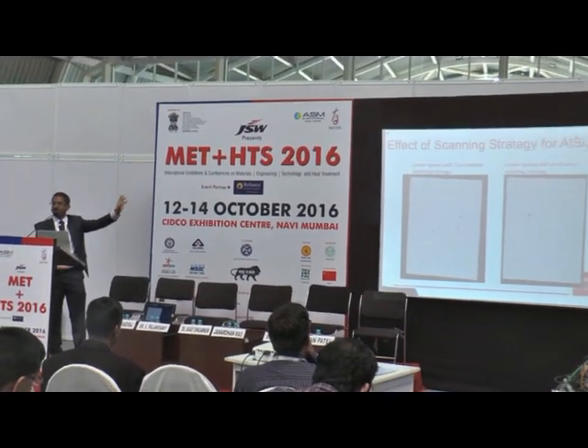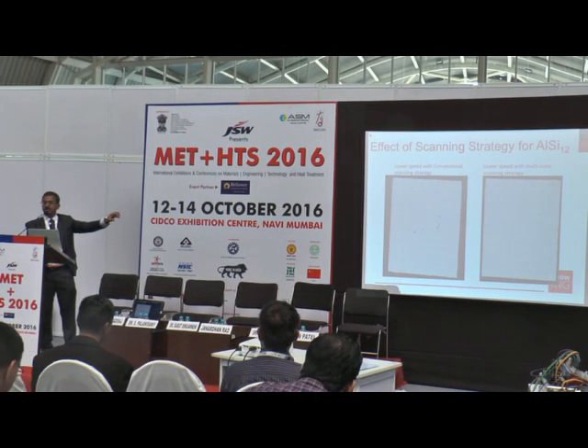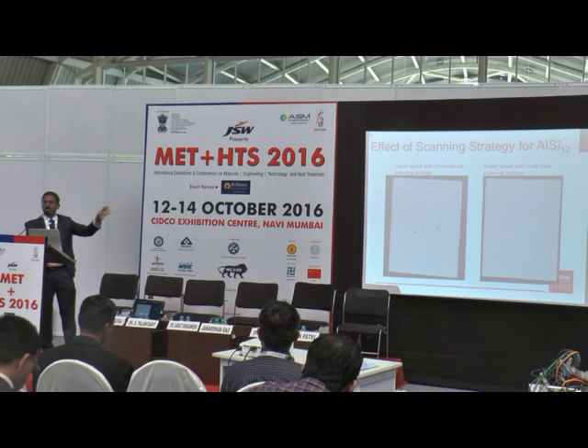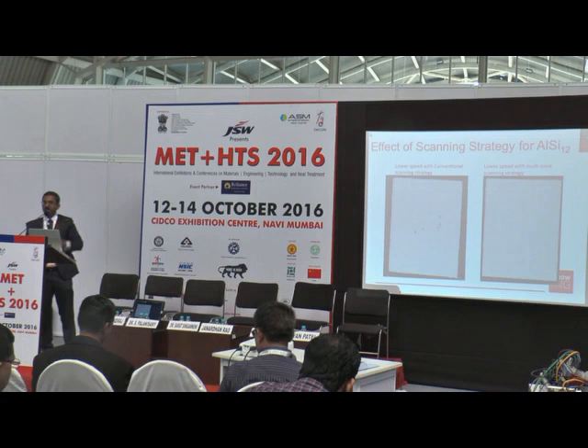Again, even with a slower scanning speed, combined with the scanning strategy, if you do the conventional scanning strategy, you can see the porosities here. The density is roughly around 99.5. At the same time, when you do the multi-zone scanning strategy along with the scan speed, you get 99.95 percent, very, very close to a fully dense part, which is really good. That's what most people are looking at, especially the machine manufacturers and the people working in aerospace and defense applications.